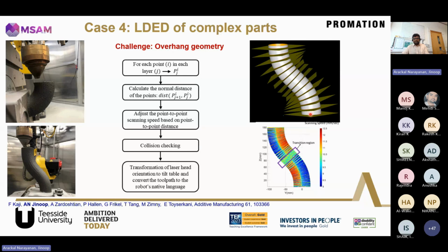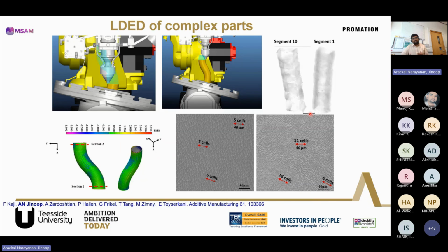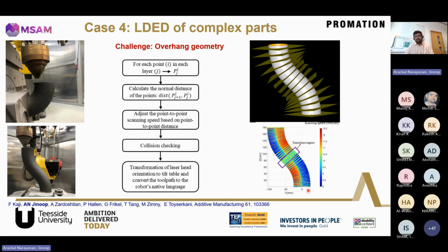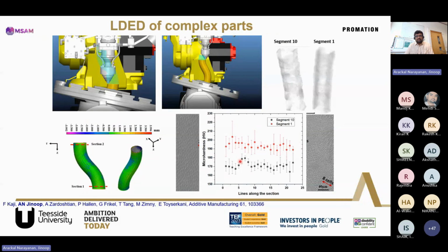So we did some sort of material analysis to understand if this has an impact on the properties. We did CT analysis, material analysis and geometrical analysis just to ensure that the properties are at par with what we are expecting and there is not huge deviation because of the variation in scanning speed within a single layer. And we could see that the mechanical properties are within a range. The structures are largely defect free. There is no huge variation in the defects that are formed in the process.